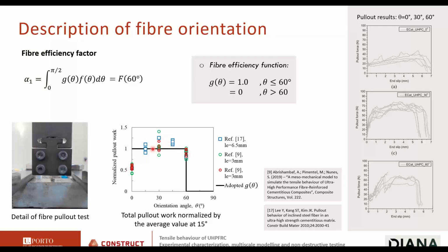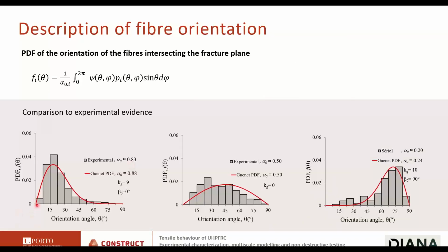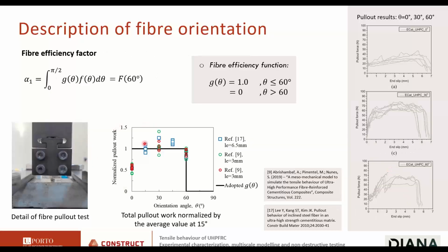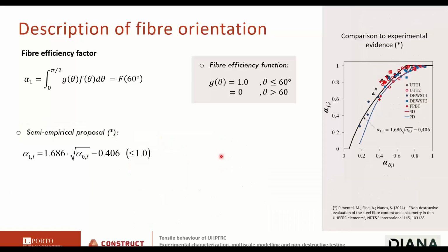The thing is that you will never find fibers at 0 degrees. Theory says that the probability of finding fibers at 0 degrees is null. So you always find fibers with some inclination. So this part of the curve is not really that important. What's important is here between 10 and 60, let's say. So a constant value is not a very poor representation of the reality, and it's very simple. And we adopted this.